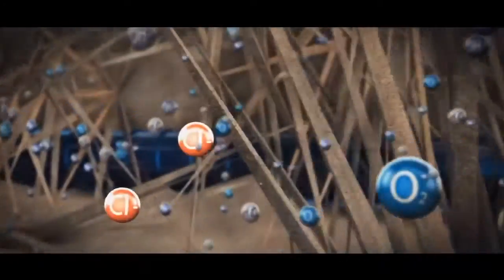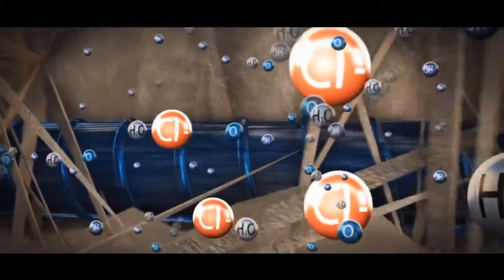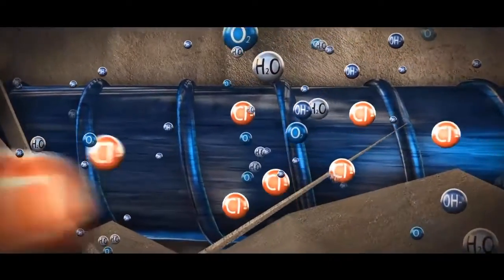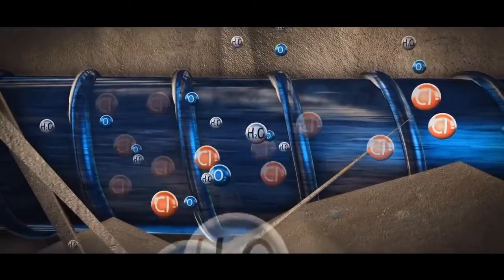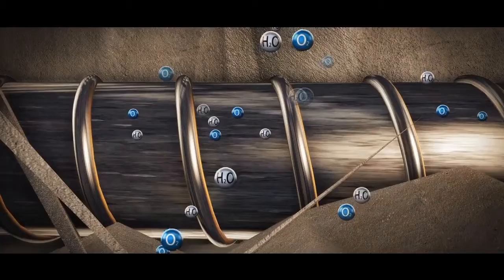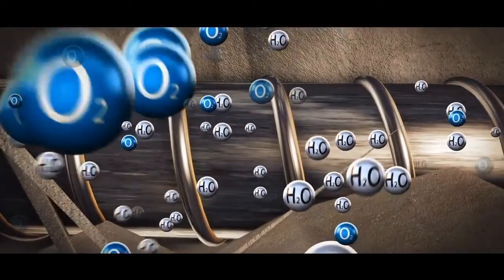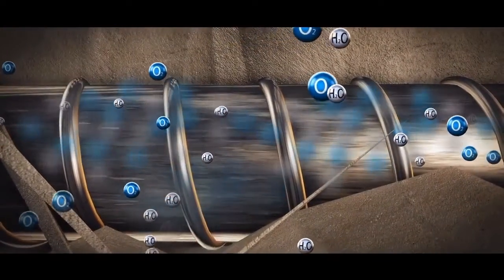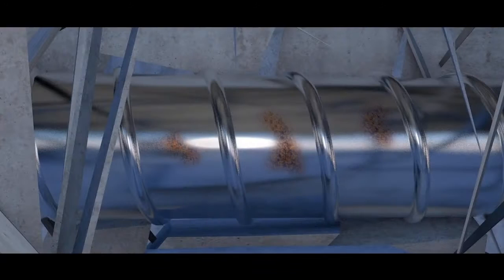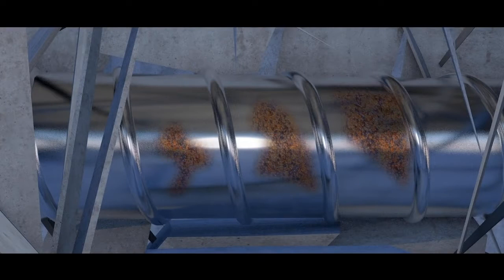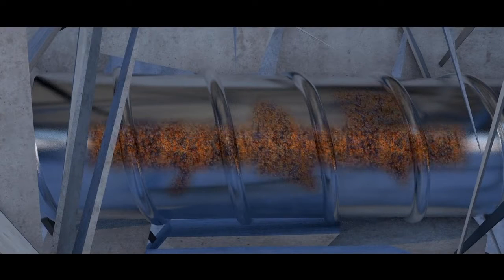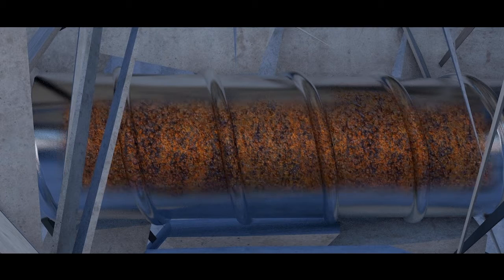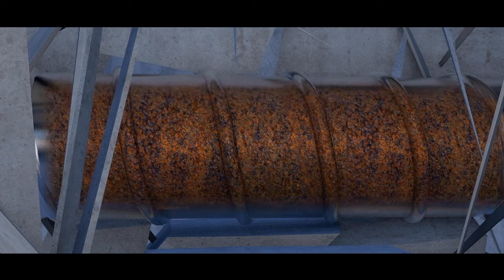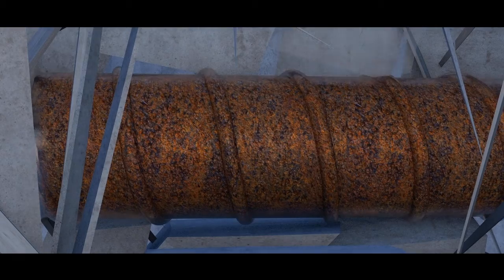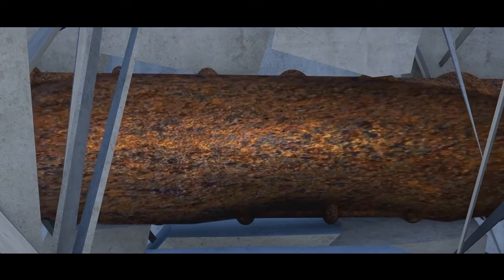In marine and aggressive high chloride soil conditions, chlorides migrate over time through concrete pores, building up at the surface of the steel to reach what is known as the critical chloride threshold, at which the passive layer breaks down. Once that breaks down, corrosion is initiated, and the corrosion product starts forming on anodic locations of the corrosion electrochemical reaction. Corrosion continues to propagate as complexes of oxides and hydroxides are formed.